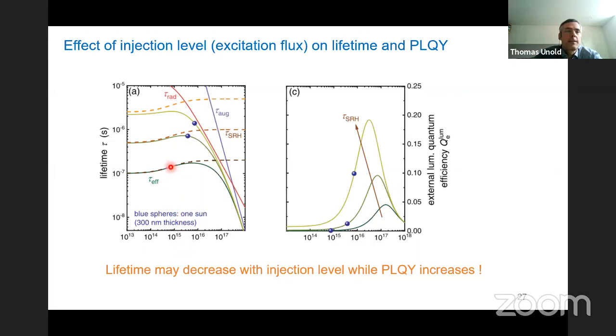And now for each of these cases, the one sun conditions are shown here as dots. And here is the external luminescence efficiency shown. You can see here, basically the lifetime mostly goes down. First it increases a little bit and then it goes down. And here for the PL quantum efficiency, it first strongly goes up and then goes down. If we pick, for instance, this case here, you can be at around AM 1.5. And if you increase the excitation density a little bit more, the lifetime you measure gets smaller, but actually the PL quantum efficiency goes up. So it shows you that it's very important to get the right excitation conditions in order to get consistent measurements on this.